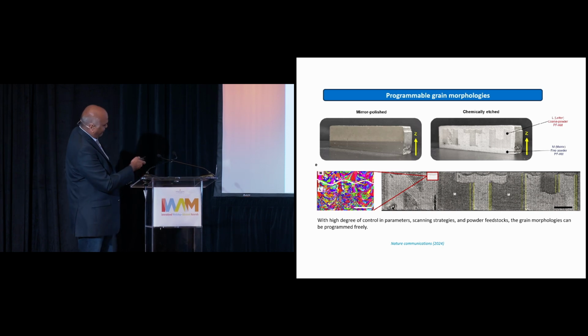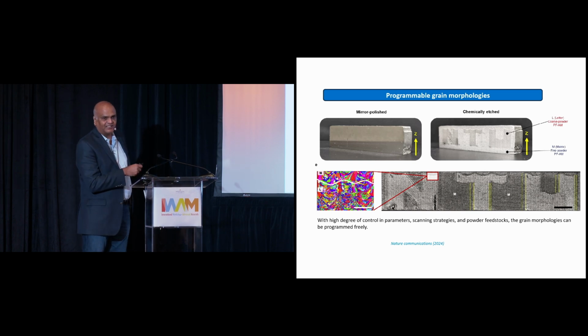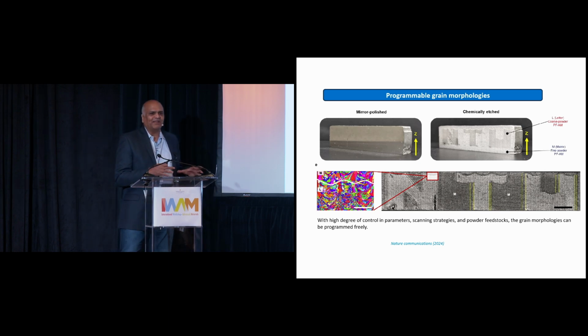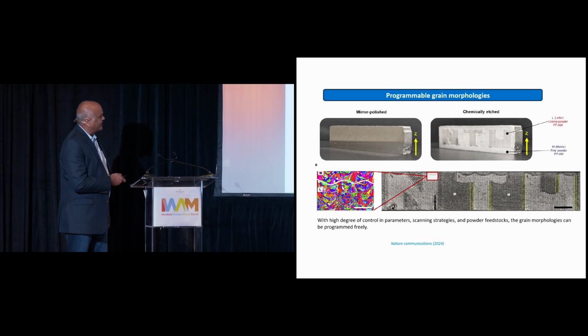If you polish this 3D printed piece of metal, you can't see this. But if you etch it, because of the different grain structures, you can see these features by varying things. So we want to be able to play around with the microstructures and do whatever we want, and this is one way.